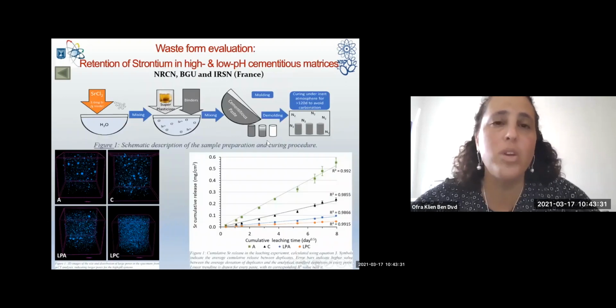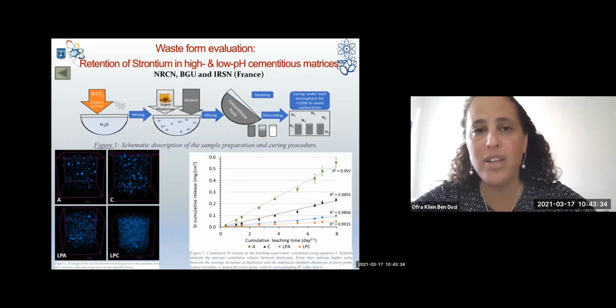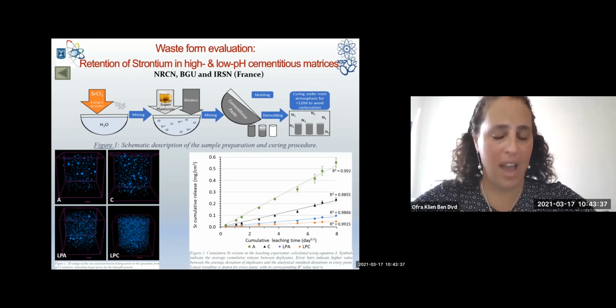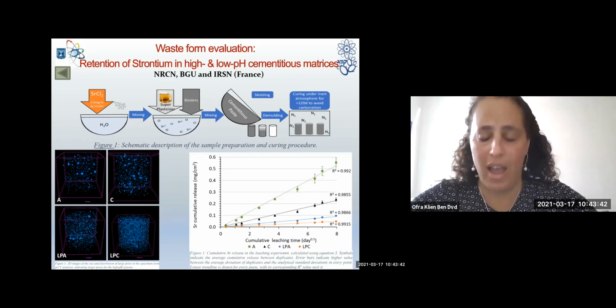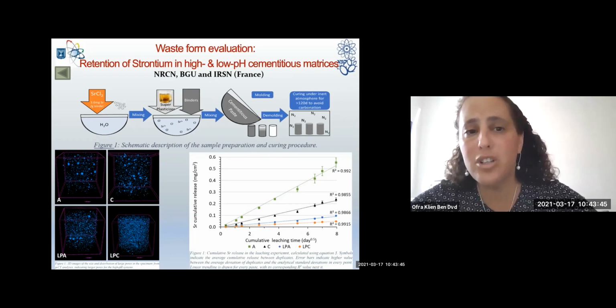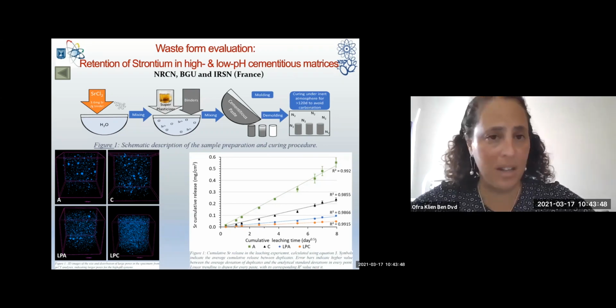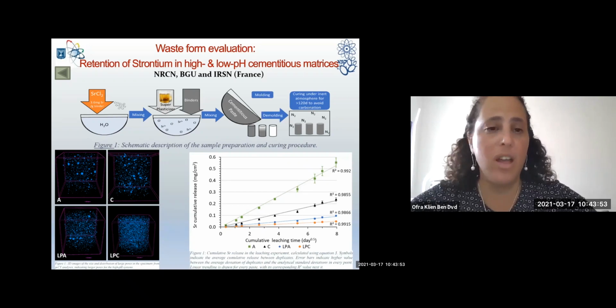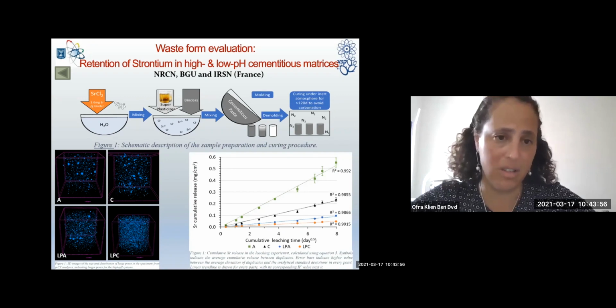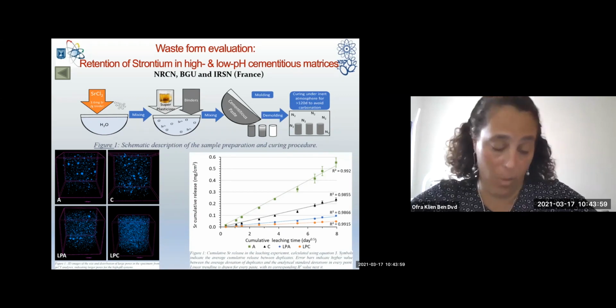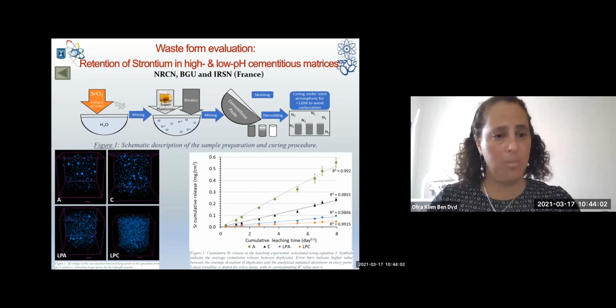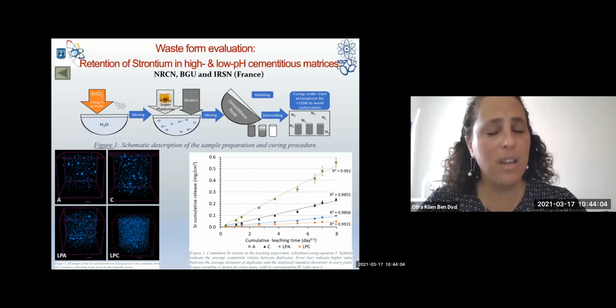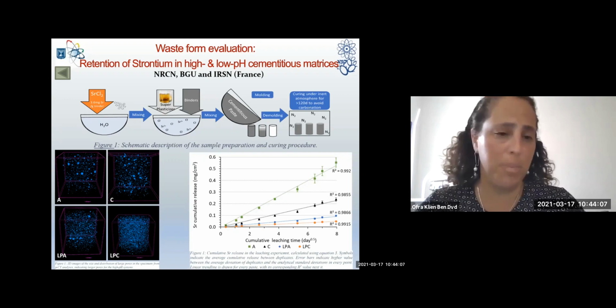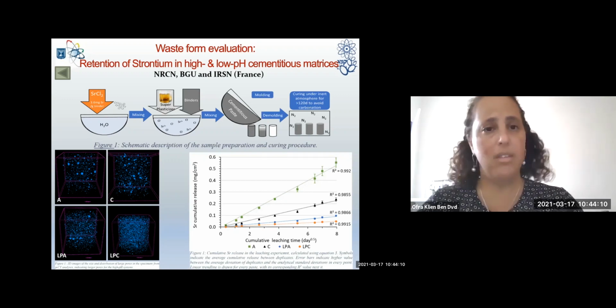So waste form evaluation, what is a waste form? When we have radioactive waste, we want to stabilize it within a matrix that won't let it migrate. And we have several matrices that are acceptable in the world, where cementitious materials are the most common one for low and intermediate level waste. However, cementitious materials have very high pH, and high pH perturbs the surrounding rock area. The rocks, when we are talking about carbonates, have a pH of about 8, and the cement can be 13, 12. So we need to decrease the pH of the cement in order to make it more adequate for the carbonate area.